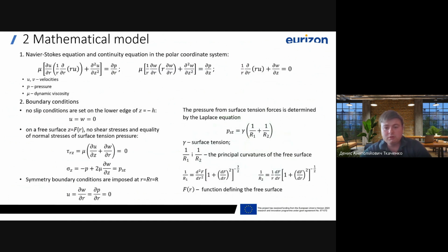The mathematical model is based on the Navier-Stokes and continuity equations in polar coordinates adapted for an axisymmetric configuration. Given the small scale and low velocities involved, we neglect gravity and inertial effects, focusing solely on viscous and surface tension forces. Boundary conditions include no slip at the bottom surface and stress balance at the free surface, where surface tension is described using the Laplace equation. Due to axisymmetry, the surface curvature is determined by two principal radii derived from the free surface function. Symmetry conditions are also imposed at the radial boundary. Together, this forms a complete model for surface leveling driven by surface tension in a viscous liquid.